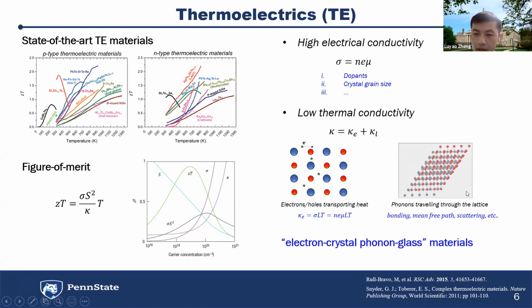So as shown here, it's the transfer of the vibration. So it depends on how strong the bonding is and how long the mean free path for the phonons is inside the material. And also if there are some impurities inside or some phase separation regions, they will generate some scattering centers. So all these affect the lattice conductivity. But overall, it's the sum of these two parts.